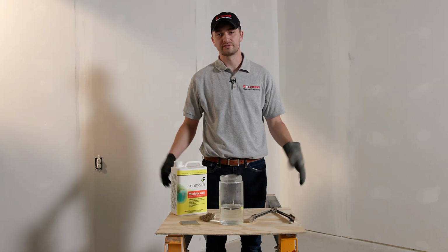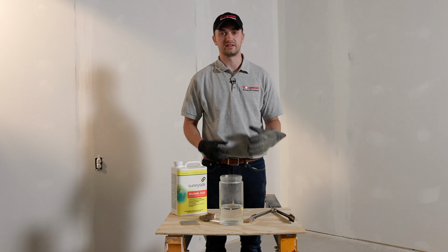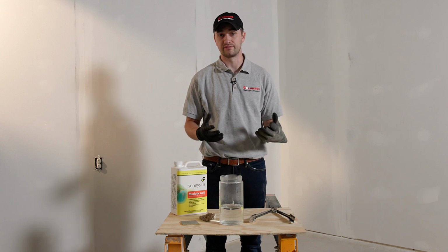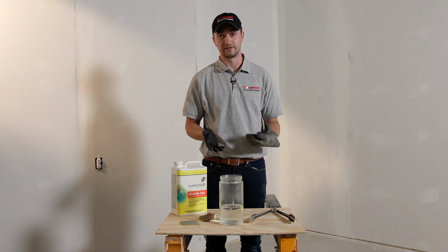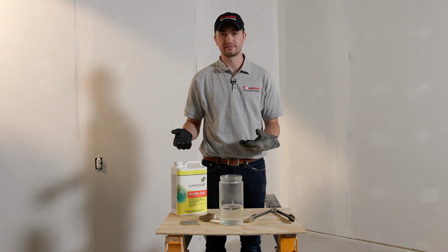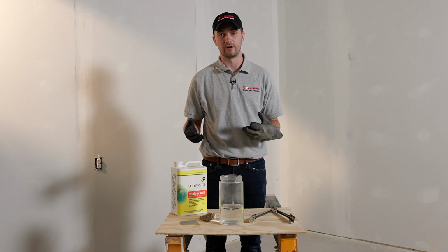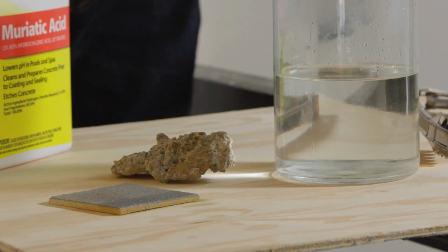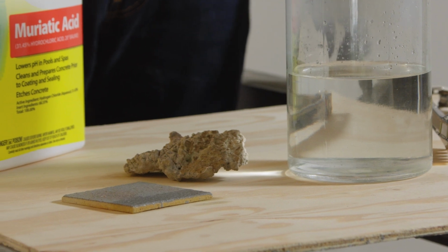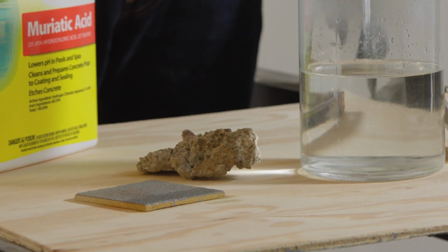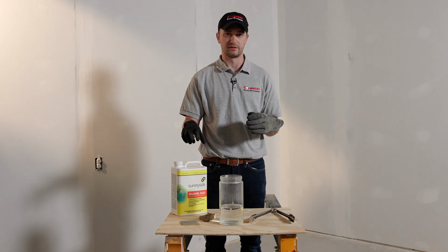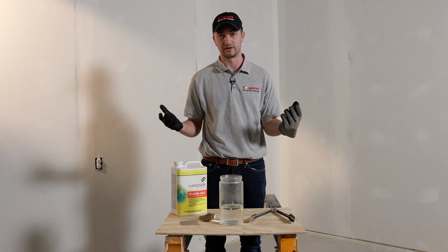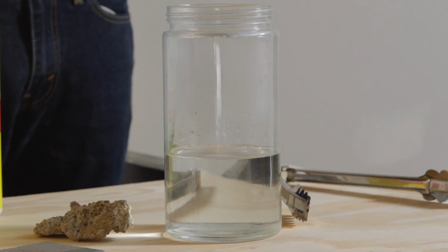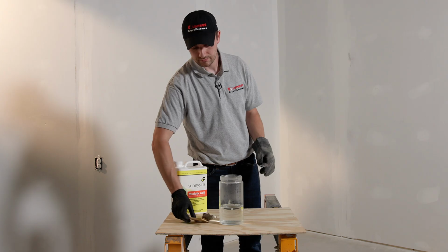So finally, urethane cement flooring systems boast extremely high levels of chemical resistance. We're gonna demonstrate this here. We have some muriatic acid, which is used primarily for etching concrete. We're gonna test that by dipping both a chunk of bare concrete into the muriatic acid, and then we are going to take a sample of the urethane cement as well into the same jar, and we're gonna see how they hold up to this acid, given a little bit of time here.